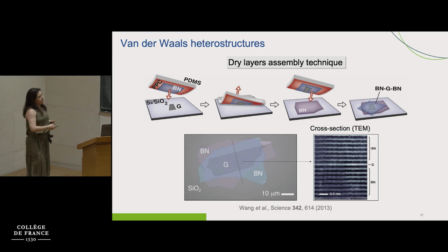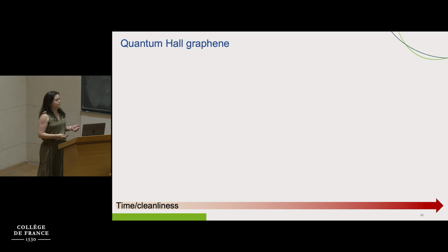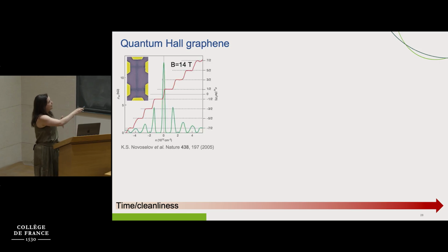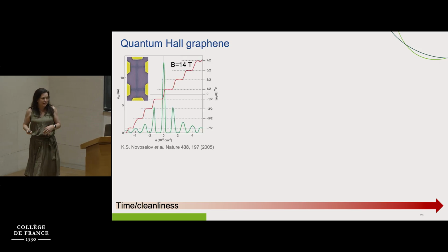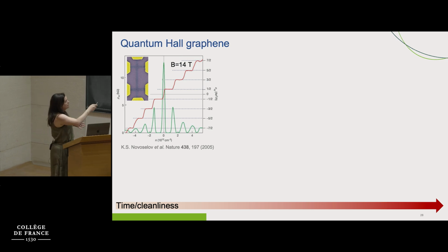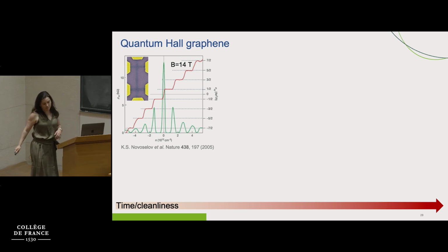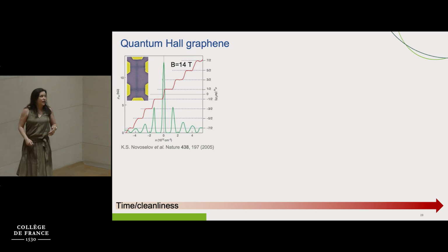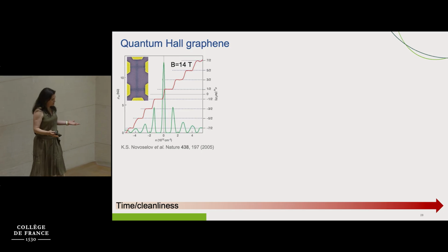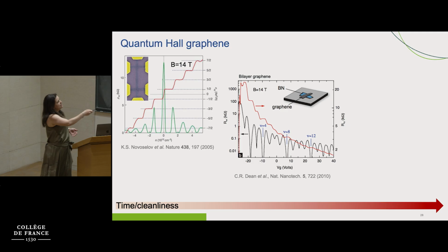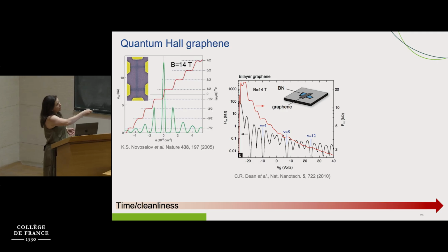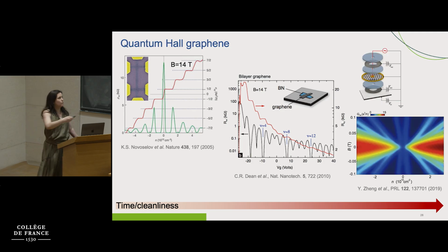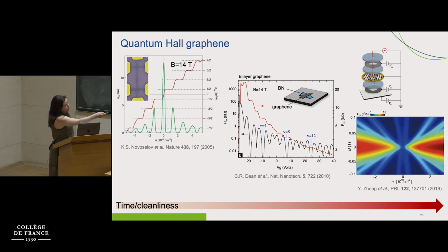So establishing this method allowed us to go from a quantum Hall effect of graphene on silicon oxide that was barely visible at high magnetic field, and didn't even show degeneracy liftings, to a system where we can observe degeneracy liftings already for the same magnetic field, and to go even further, one where we can observe the integer quantum Hall effect at very low magnetic fields with a quite complicated structure, I must say.